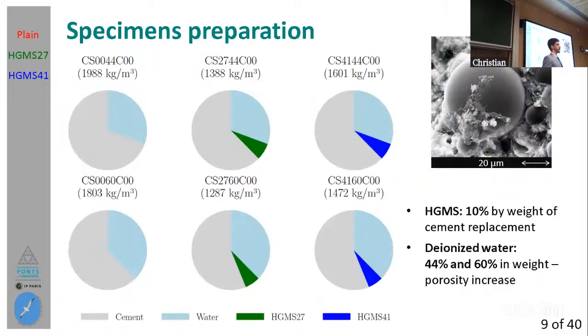As for the specimens that I have been using throughout this thesis or this project, we can distinguish these 6 different specimens. In the first column, you will see the plain cement paste, the red ones. The only difference between these two is the water to cement ratio, which is 0.44 for the one on the top and 0.60 for the one on the bottom. You can see that in the name, 44 here and 60 there. Then 00 stands for no replacement of cement by hollow glass microspheres.